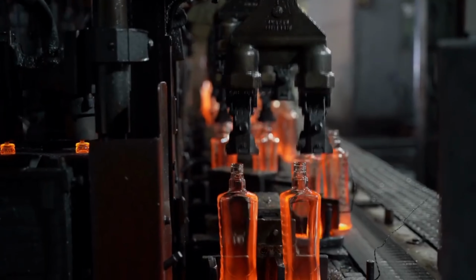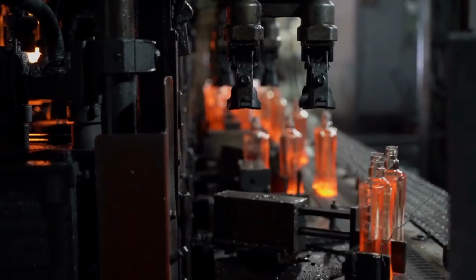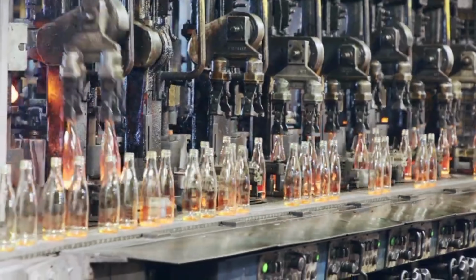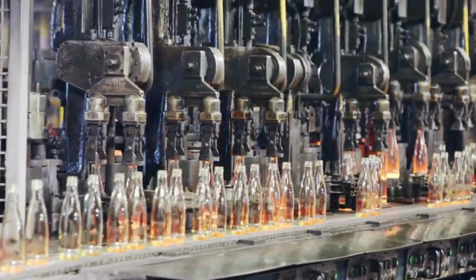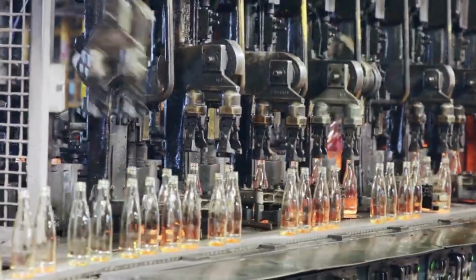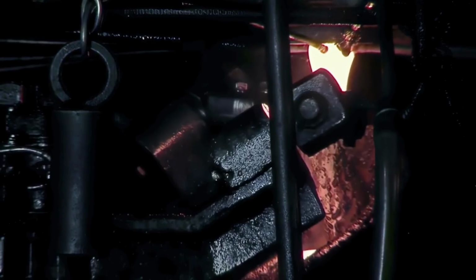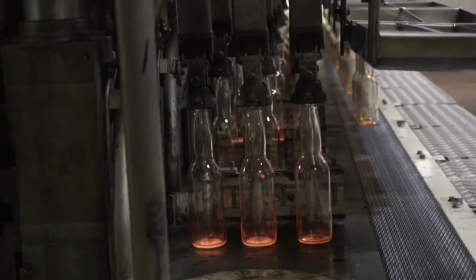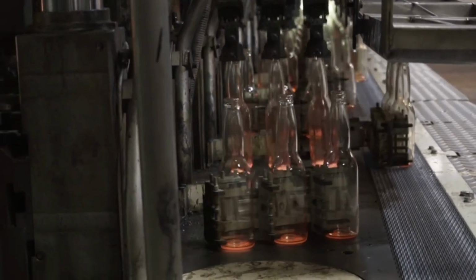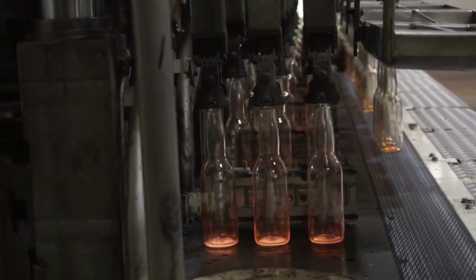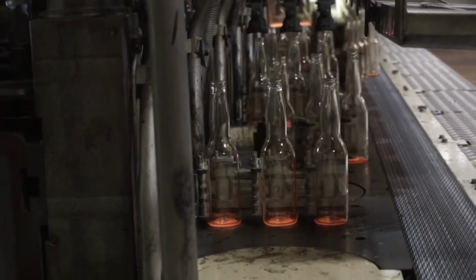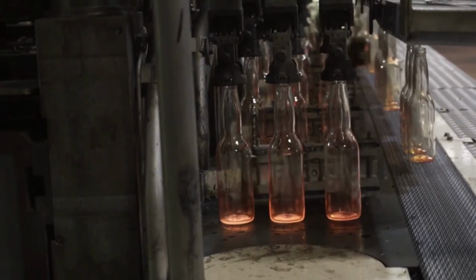But in this environment, speed is everything. Modern IS machines can produce up to 700 bottles per minute across multiple sections, requiring mechanical precision so reliable that a single misaligned mold, temperature fluctuation, or slow shear cut could ruin thousands of bottles. And to prevent that, sensors constantly measure gob weight, mold temperature, air pressure, and timing, correcting errors in real time to maintain consistent quality.